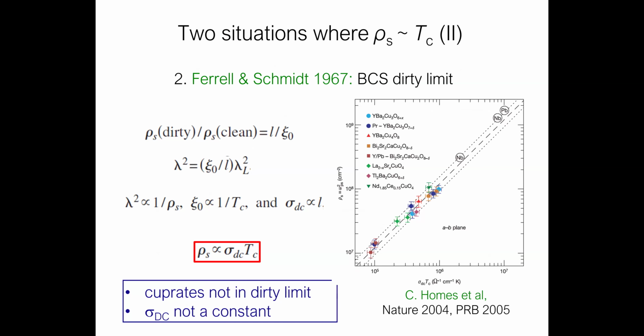There's another situation where ρ_s should be proportional to T_c, and that's an s-wave superconductor in the dirty limit. So if you take the ratio of ρ_s in the dirty limit to ρ_s in the clean limit, you get the mean free path divided by the coherence length. The penetration depth in a dirty system goes like ξ over l times the clean London penetration depth squared.